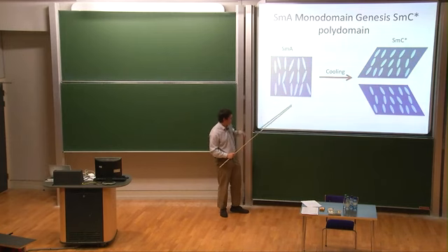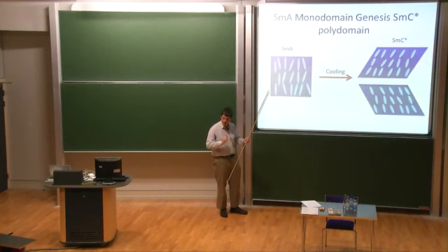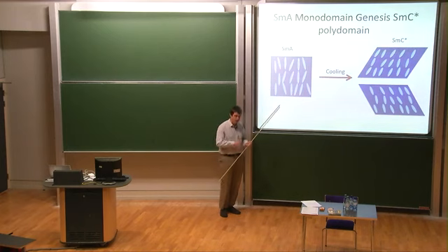The reason I'm saying that is, first of all, it illustrates the general point. I think the general guidance on these is if you cross-link in the high symmetry state, so in a state which has macroscopic symmetry, and then you break the symmetry once you're a solid, you recover a macroscopic soft mode. If you don't, you don't.